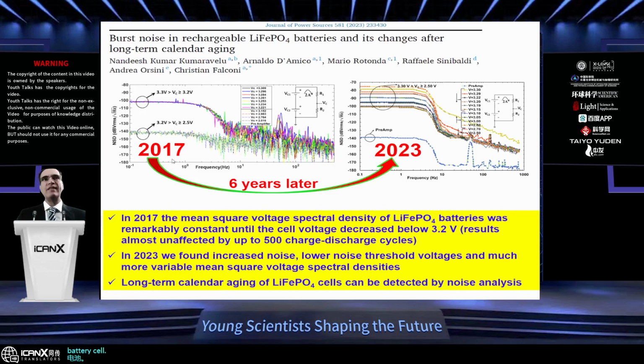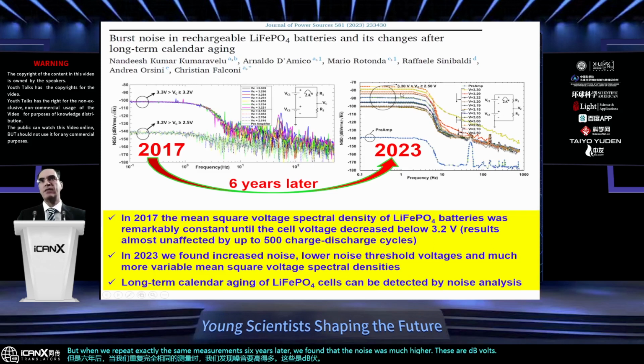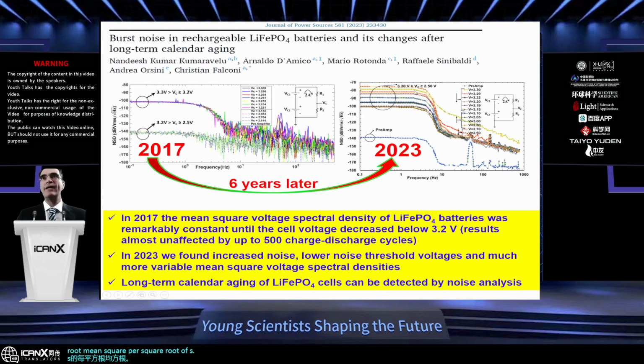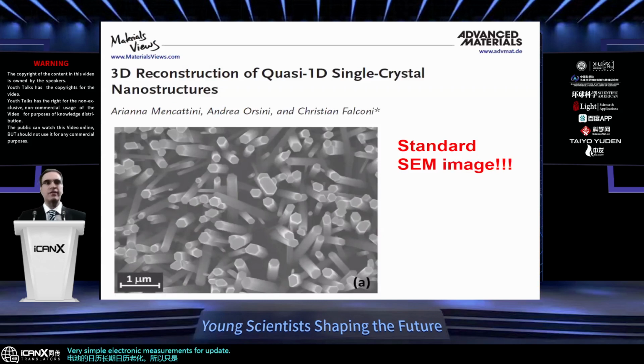But when we repeated exactly the same measurements 6 years later, we found that the noise was much higher. These are dB volt root mean square per square root of hertz, much higher. And also there was high noise even when the battery cell was discharged. So we observed for the first time that noise measurements can be used for predicting the long-term calendar aging of battery cells. So just very simple electronic measurements for obtaining important information.